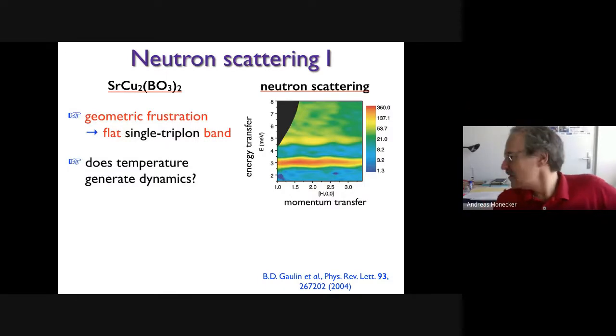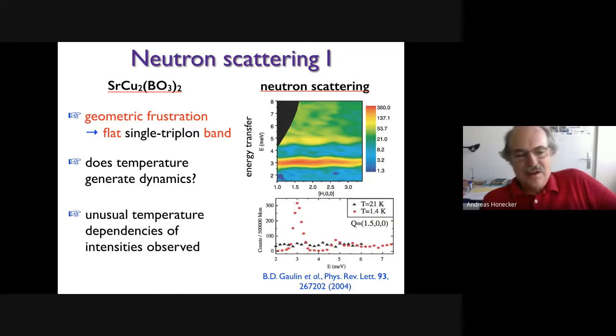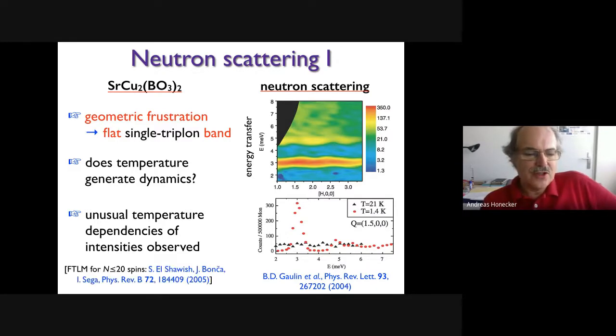Now you might ask yourself questions like, well, if the dynamics is absent at 0 temperature, does temperature actually generate dynamics? In fact, already at that time, people did look at temperature dependence, and going from 1.4 Kelvin to 21 Kelvin, the dynamic response actually changed a lot. I should also mention that there was a study at roughly the same time, a theoretical study by Janos Bonka and collaborator, who did a numerical investigation of a quite small system. And well, since the system is very small, I'm not going to comment further on that particular investigation.